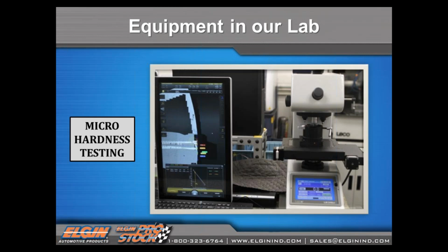A micro hardness tester is a lab piece of equipment that takes that mount we had made and cross-sectioned. If you remember, we had that etched mount of a couple of different carburized or case hardened parts. We mount that underneath a microscope, and there's a little hardness indenter, just like on a Rockwell tester. The machine will automatically measure the hardness of that case at the surface, then work its way in towards the core, and we can tell it to take a hardness reading every 1/1000th of an inch, and that's why it's called micro hardness. Then the computer hooked up to it will illustrate what that hardness band is and where it found Rockwell C50.